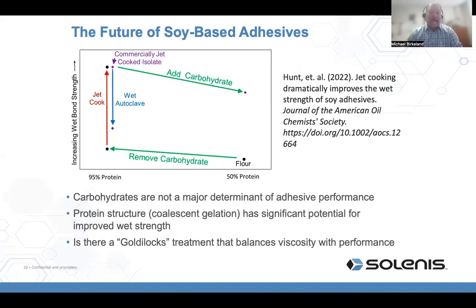Most of the commercially available, if not all, isolate is jet cooked, and so in this experiment they also obtained a jet cooked isolate material, added the carbohydrates back, which again you can see did decrease the wet strength by approximately the same amount that was increased by removing it in the regular flour material. So the carbohydrate really is, I think there were a lot of questions for a while, is the carbohydrate just a filler? Is it doing anything? And I think the answer is no, based on this material. But interestingly, if you take that commercially jet cooked isolate material and you then put it in a wet autoclave, you can actually lose a substantial amount of the adhesive capability.